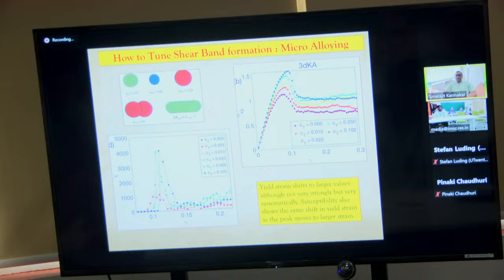Then the next question that we had in mind: how to do microalloying which will be applicable even in, let's say, experiment, because this kind of random pinning will be impossible to achieve. This is doable in colloidal experiment, but not in molecular experiments. So we proposed that if we introduce particles which are bigger in size, then these big particles will have relaxation times which are much larger than your host. So they will have much smaller diffusion coefficient than the medium particles. And over a time scale of the medium relaxation time, this particle can behave like a soft pin particle. We tried this concept and studied the yielding process in a setup where you introduce particles which are twice the size of your host particle.